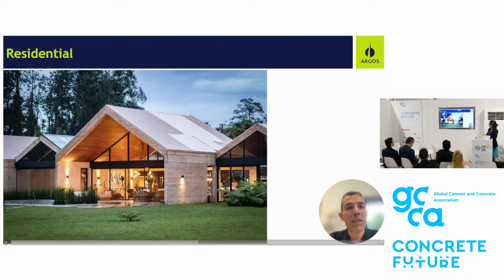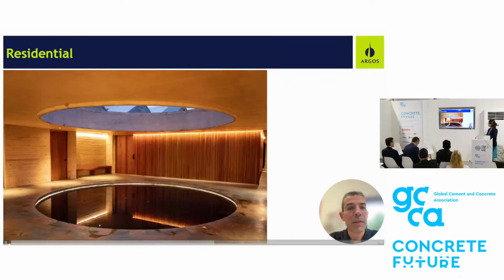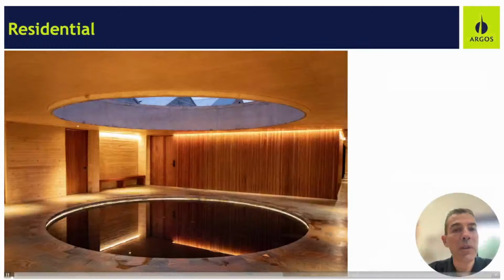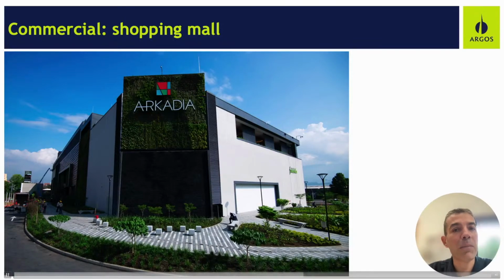This first application is a housing solution, a very high-end application, where concrete was exposed, so color, finishing, and in general, all the properties of architectural concrete were needed. In this picture, we're showing some decorative concrete applications where you can see, both at the roof and at the wall on the left side, the finishing that we had with that concrete. This is a commercial project in Medellin. It's called the Arkadia Shopping Mall, and it was completely built with this limestone calcined clay cement from Rio Claro.